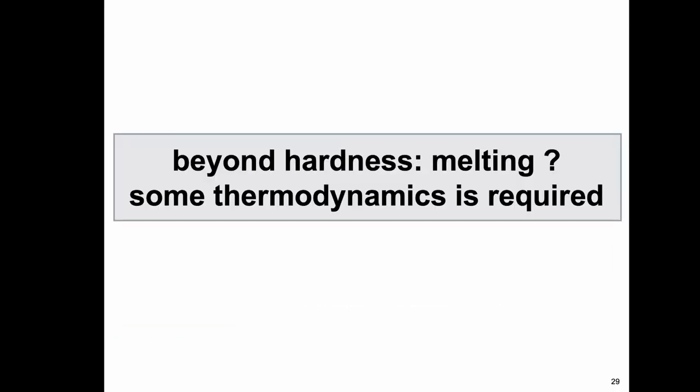Hardness, we have fixed. What about melting? The melting is a problem, because melting is even more complex than the entropy. To get the entropy, we need to increase the temperature and run molecular dynamics, and see when the order changes, so we might identify an order-disorder descriptor. Then by monitoring this order-disorder parameter, which is usually related to the bond distances or the number of bonds, we identify the melting. This is very complicated. It can take forever, even more than calculating the entropy.